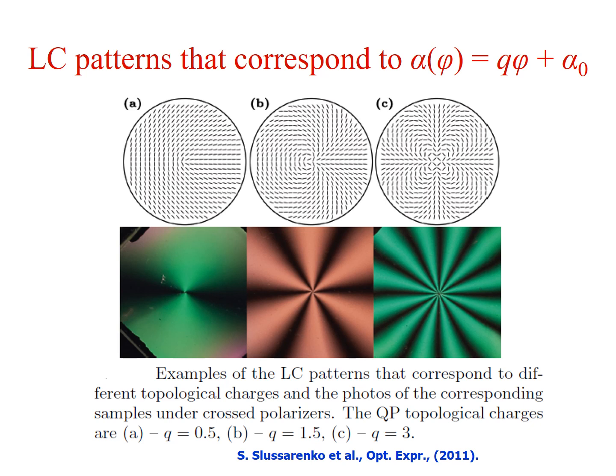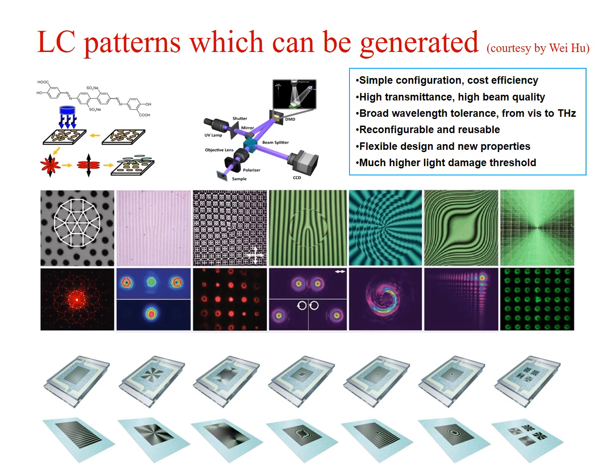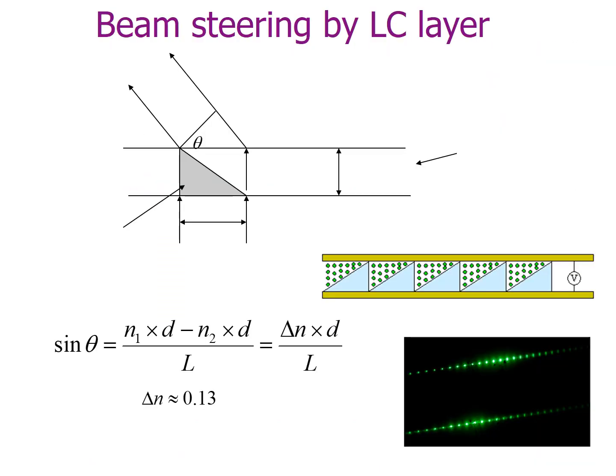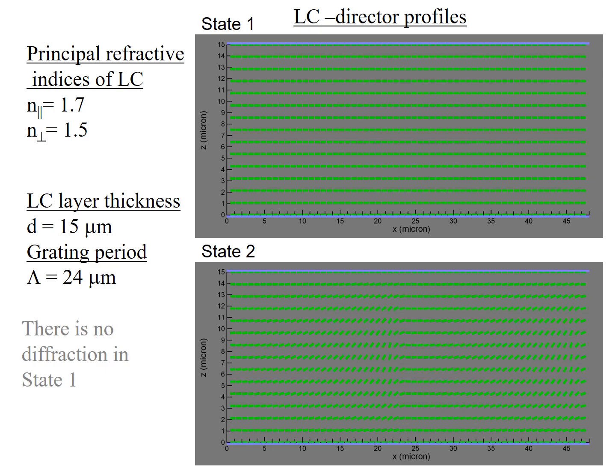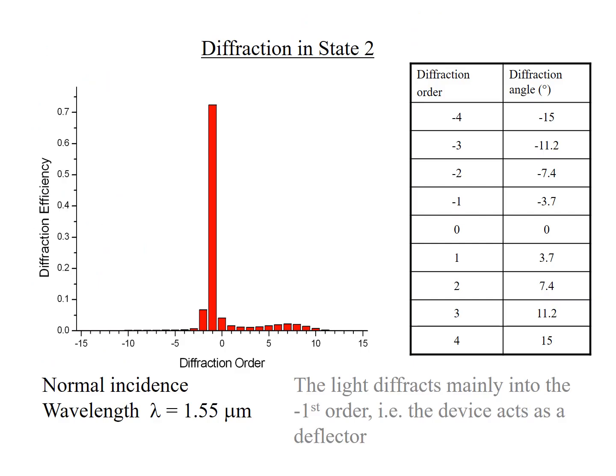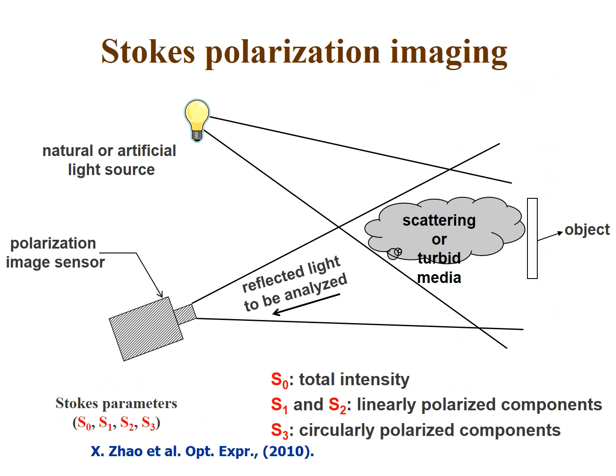if you have Q plates, we can also make Q plates for optical data processing, in particular pattern recognition. If we have a digital mirror device, for instance, which has been done by Professor Wai Hu in the Nanjing laboratory, we can have high transmittance, broad wavelengths, flexible design, and excellent configurations. So we can write many different optical pictures, not only on glass but on flexible substrates. We can also foresee beam steering elements if we can get a special configuration of liquid crystal. And these beam steering elements can also be done using liquid crystal alignment. So, for instance, if you would like to change the beam from 0 to minus 1 to about 4 degrees, you can get very high diffraction efficiency for aligned liquid crystals.